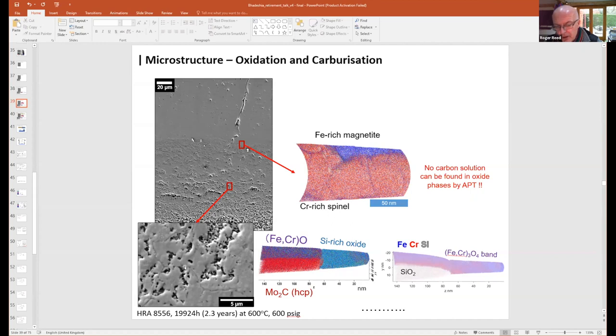And in fact, recently I saw some measurements made by Phil Withers' group, I think, where they had used very high resolution tomography and were able to show that these pores are interconnected in three dimensions to give you a path for the transport of the CO2 gas through the scale. So that probably explains why we're able to get the carburization of the underlying structure without seeing the CO2 or carbon in the scale. Many thanks. Thank you for the question.